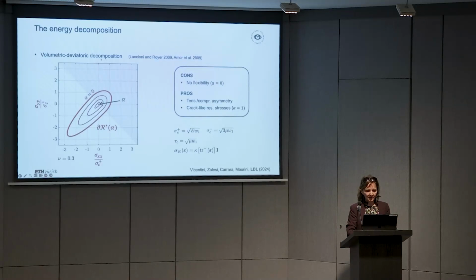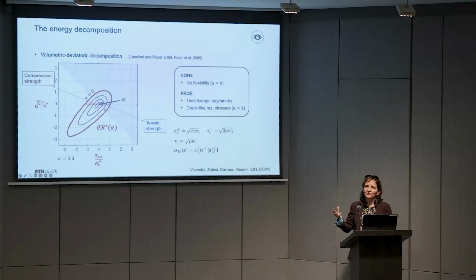So now let's look at the volumetric-deviatoric decomposition. You see here that the tensile strength is this one. So first of all, the shape is no longer an ellipse. You see that now this is elongated towards the compressive quadrant. But the tensile strength and the compressive strength are no longer the same, but the compressive strength is really marginally higher than the tensile strength. I'm talking about absolute value, of course. Marginally higher. So this depends on the Poisson's ratio, but for common Poisson's ratios, this will be 20%, 30% larger than the tensile strength. And we know for brittle materials, this is way too low. I mean, typically brittle materials have a compressive strength that is 1 order of magnitude larger than the tensile strength.